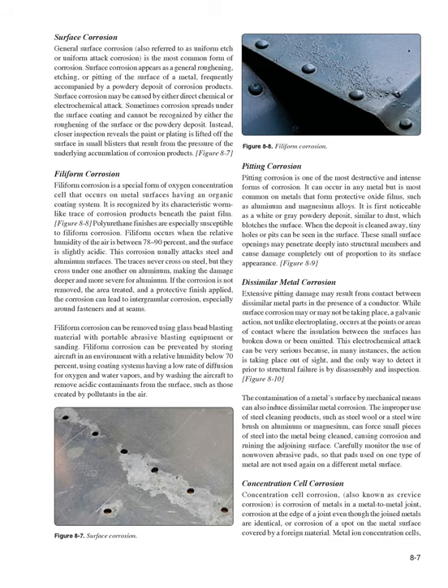Figure 8.8, polyurethane finishes are especially susceptible to filiform corrosion. Filiform occurs when the relative humidity of the air is between 78-90% and the surface is slightly acidic. This corrosion usually attacks steel and aluminum surfaces. The traces never cross on steel, but they cross under one another on aluminum, making the damage deeper and more severe for aluminum. If the corrosion is not removed, the area treated, and a protective finish applied, the corrosion can lead to intergranular corrosion, especially around fasteners and at seams.